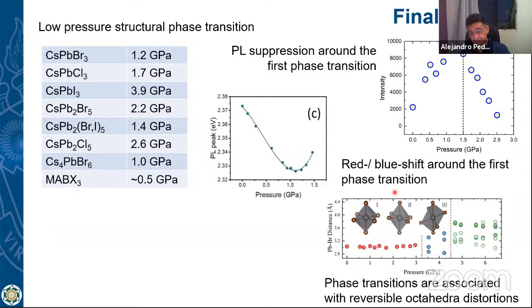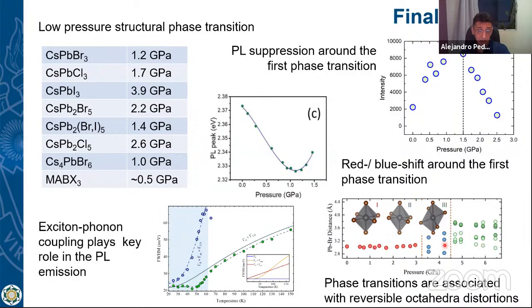And also the phase transitions are always associated to distortions of the halide octahedra, which are always reversible. And the Raman and vibration spectra and the photoluminescence spectra are strongly related because the exciton-phonon coupling plays a very important role in the photoluminescence emission.